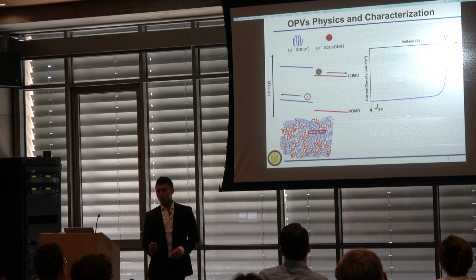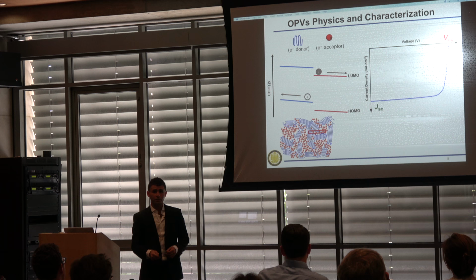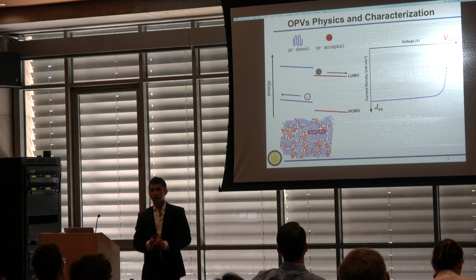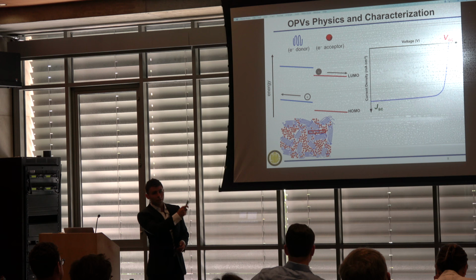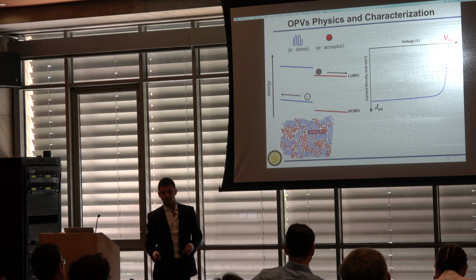We characterize these solar cells. The main method of characterization is what we call the JV curve. So J is the current density and V is the voltage. You sweep the voltage and you measure the current density as you sweep voltage through. And you notice it's a bit of a rectangular shaped curve. And the more rectangular like it is, the better actually.